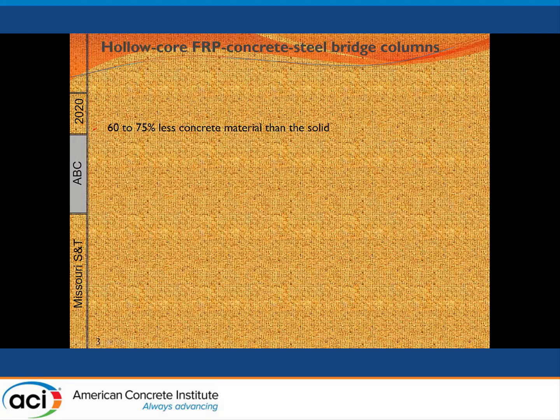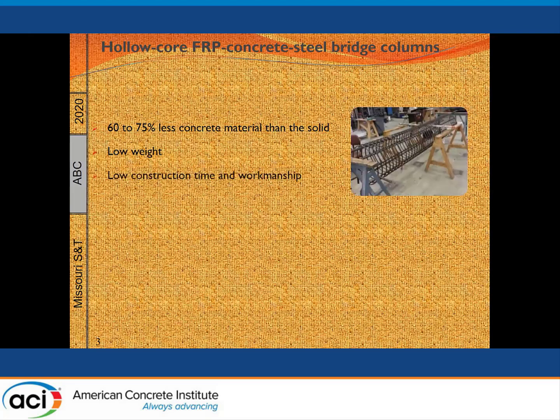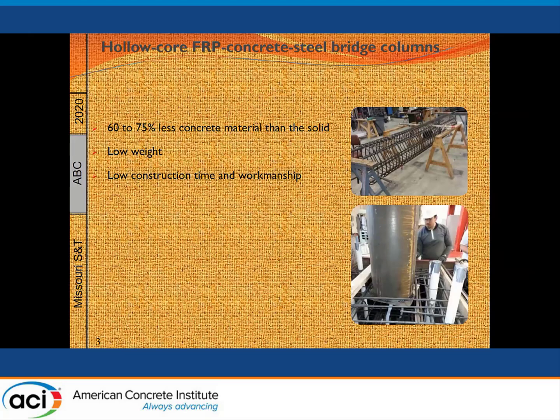So what is the advantage? Well, because of the hollow tube, you can cut up to 75% less concrete material. Of course, you would get lower weight and lower construction time. So, for example, over here, this is our reference column with the reinforced concrete columns, the spirals over there. It took my student about 2 weeks to do the fabrication of the columns. The other one that we propose, the two tubes act as a stay-in-place formwork. So you just fill in between. So it's literally a few hours just to fix the two tubes in place and then fill in between with concrete. So you cut a few weeks to a few hours.